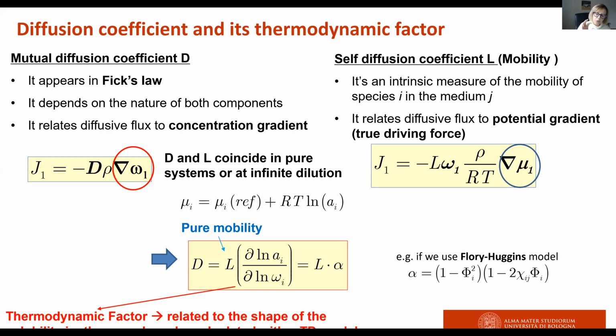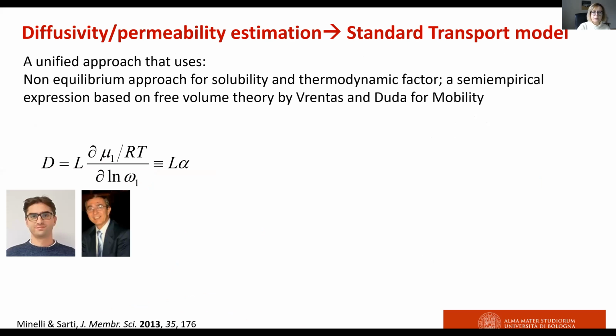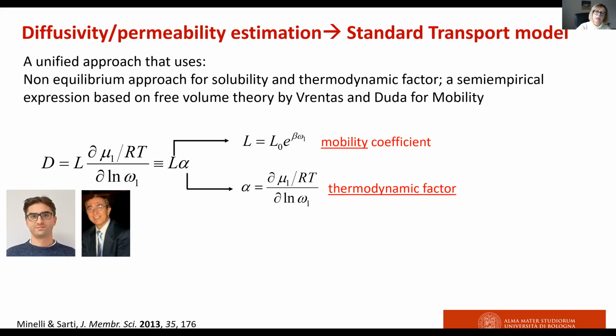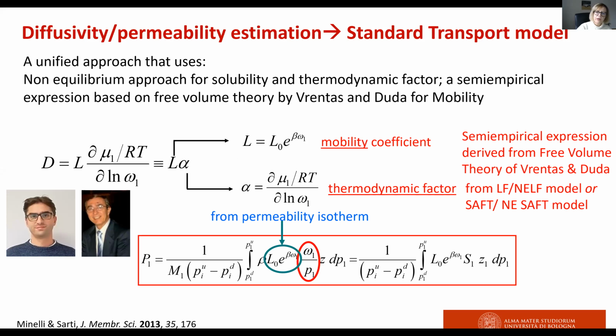These concepts were combined with the tools for the calculation of solubility by Minelli and Sarti, who developed a unified approach that goes under the name of standard transport model, that allows to simulate both the solubility and the diffusivity within the same framework. In particular, they used the non-equilibrium model to find the solubility contribution to the permeation, and the thermodynamic factor in the diffusion coefficient. And they used an empirical law based on the free volume theory by Vrentas and Duda for estimating the mobility. And finally, they found a unique expression for the permeability as a function of the pressure on the downstream and upstream sides of the membranes.